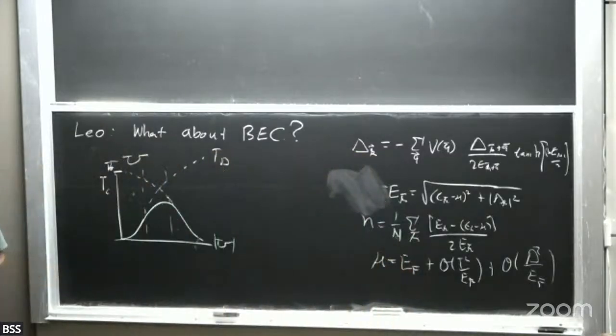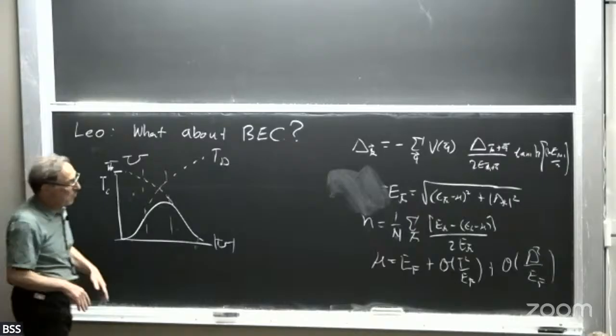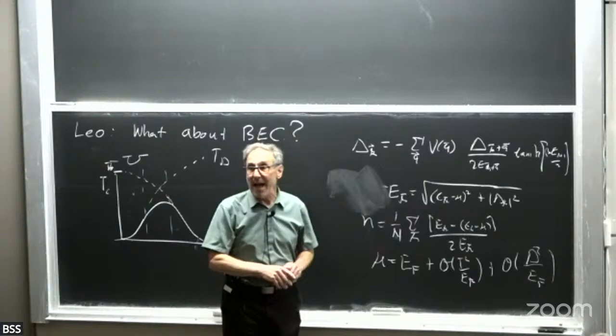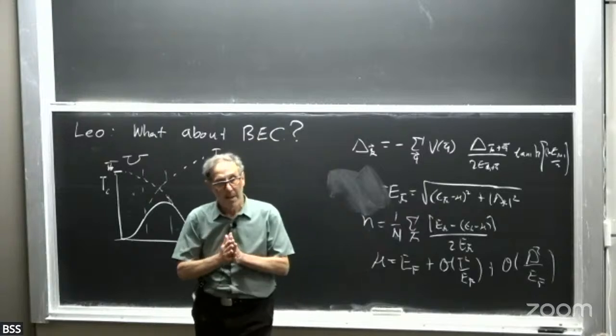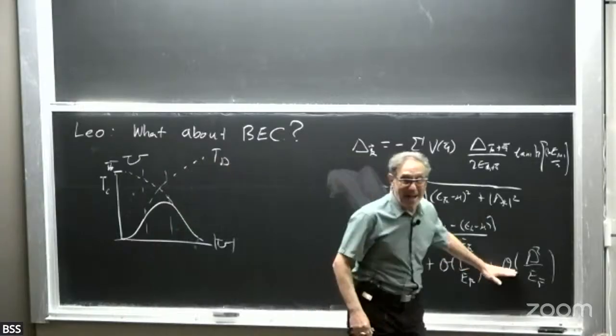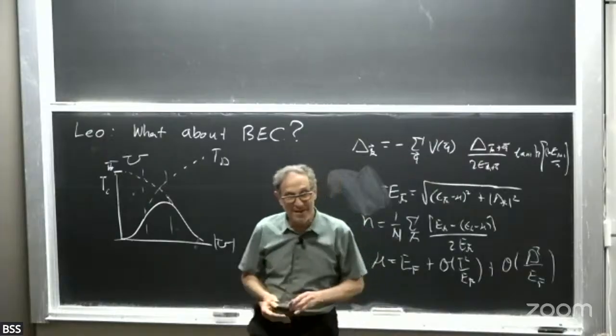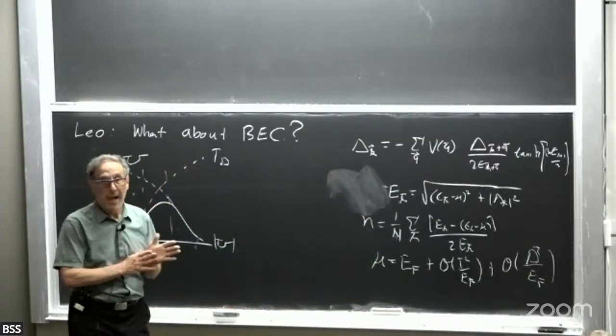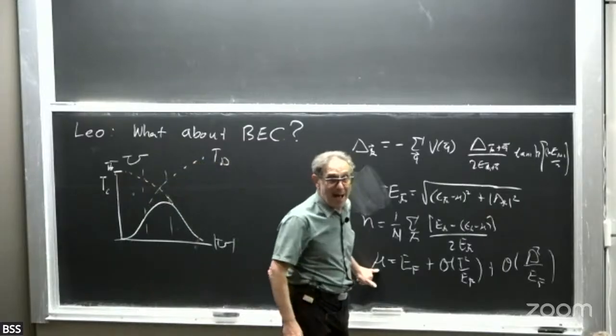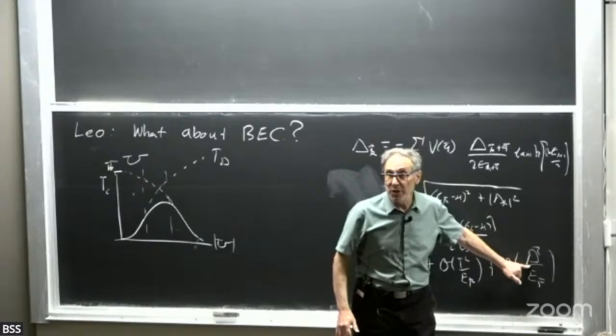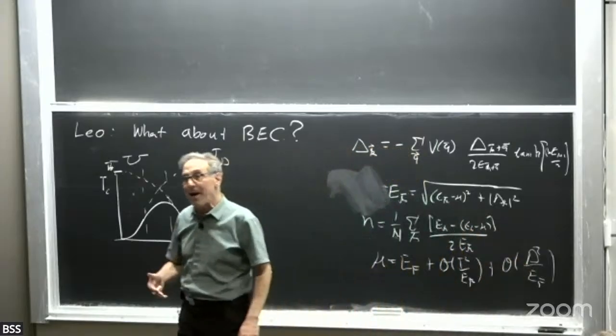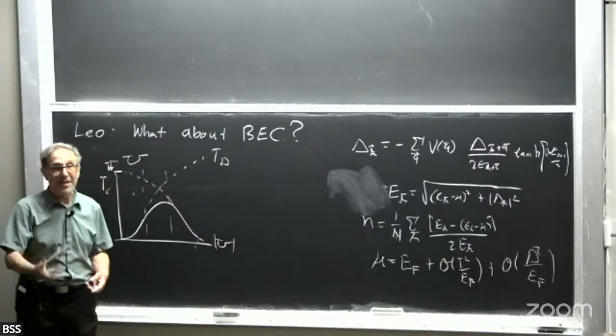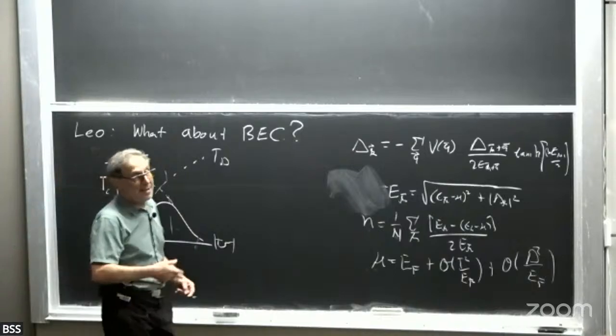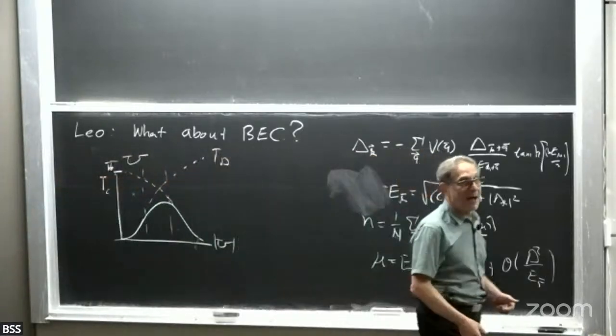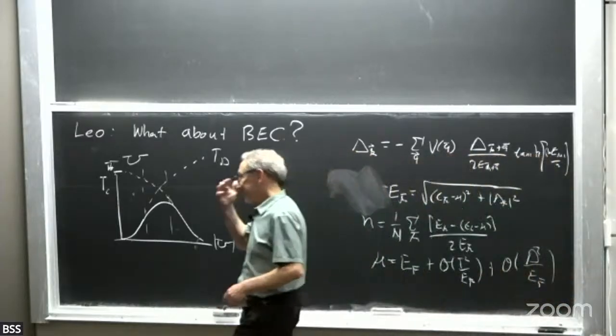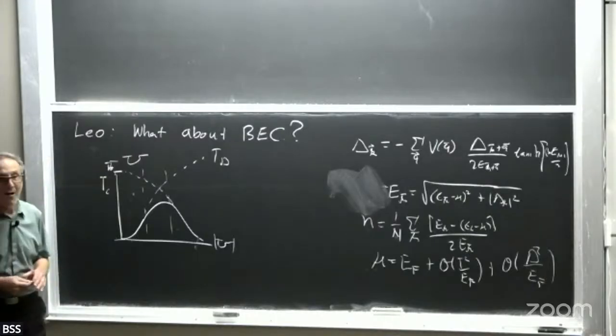And if we have a band bottom, we turn up the interactions, we can see the chemical potential start to move down toward the band bottom. It depends on the band. It's got a rho prime of E_F in it. Because this is of order E_F, as a fraction in usual superconductors, this is of order delta over E_F squared, which is Tc over E_F squared. So if Tc is 10 Kelvin and E Fermi is 10 to the 5th Kelvin, this is a 10 to the minus 8th effect. It's really tiny. Don't worry about it.